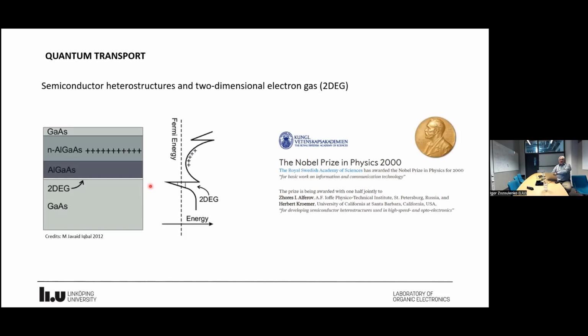And this interface is, in principle, a perfect interface. There are no impurities there because the dopants are situated far away. And therefore, in such a system, you have this two-dimensional electron gas on the surface, which has extremely high mobility and extremely high conductivity.